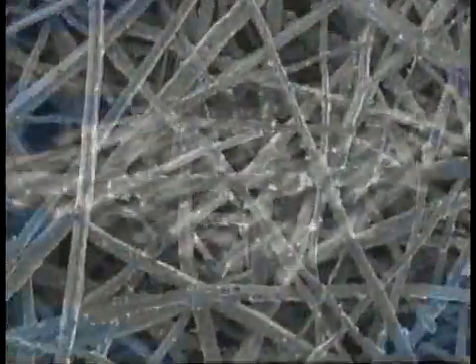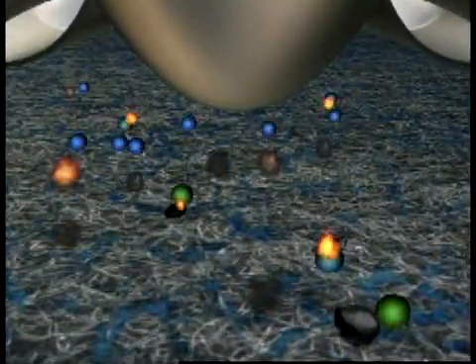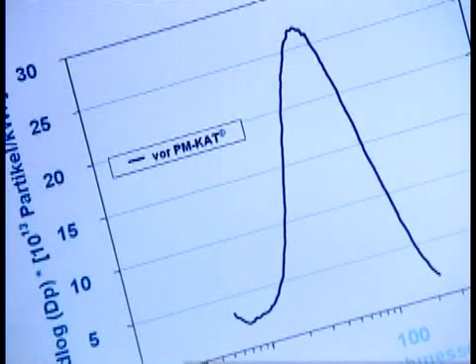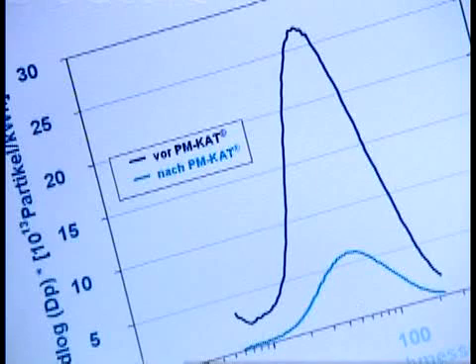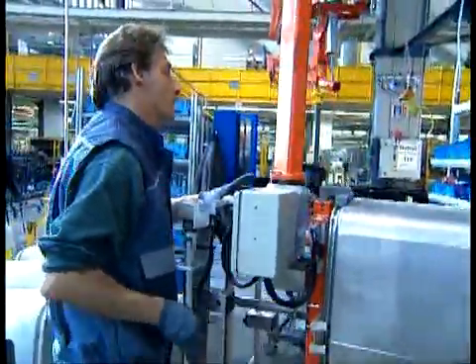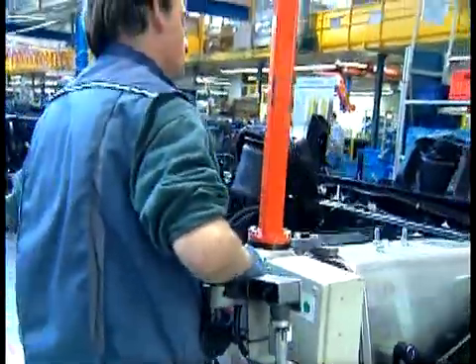The PM-KAT is designed so that soot particles are caught in a fine metallic membrane — an open system that does not clog up with soot as conventional particle filters do. The trapped soot particles are burned with NO2, combusting into carbon dioxide with no additional heating required. In the engine lab, the PM-KAT lives up to high expectations: the soot trap reduces diesel particle emissions by up to 90%. Once ready for serial production, the soot filter and catalytic converter fits easily inside the muffler, allowing it to be installed in existing vehicles as well.